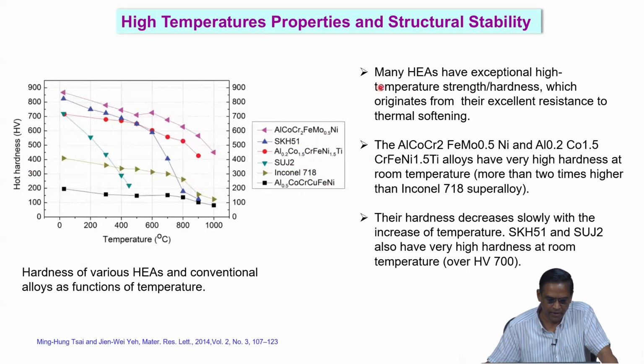So you have evidence that many high entropy alloys have an exceptional high temperature strength and hardness, which originates from their excellent resistance to thermal softening. Okay, this is the bottom line. They are quite resistant to thermal softening. How do we know? You can see that the conventional alloys like SKH51 or SUJ2, how do they react? There is a sudden drop. The moment the temperature increases, you can see a drastic drop in the hardness. And if you look at all the high entropy alloys, the change is quite gradual, right? So that means the thermal softening is highly restricted here.